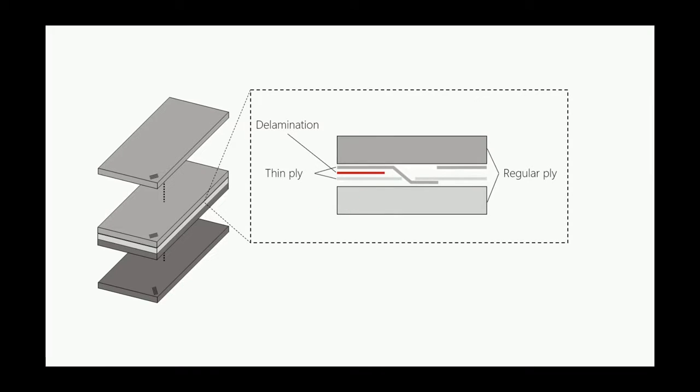In the case of compression after impact, we know that delaminations will occur at each interface at which there is a fiber orientation angle mismatch. By choosing the fiber orientations for the reinforcement units the way we have, we ensure that delaminations only occur at the midplane of reinforcement units, where they can be bridged by the tabs. This increases the effective fracture toughness, which retards the delamination growth, and thus makes the laminate as a whole more damage resistant.